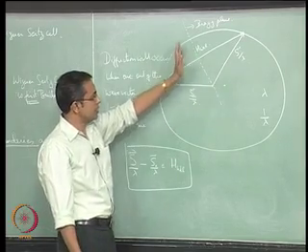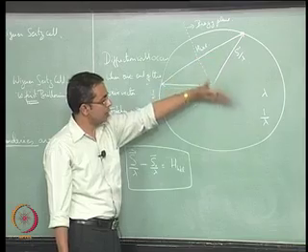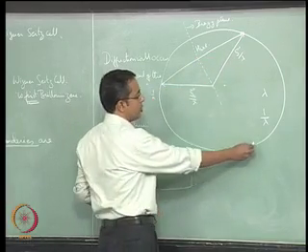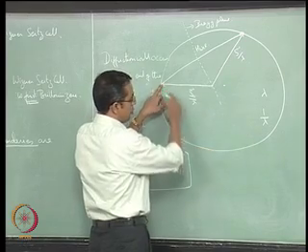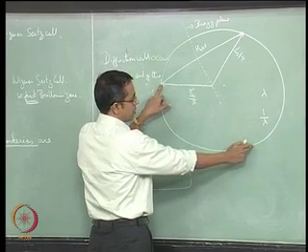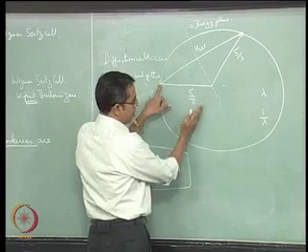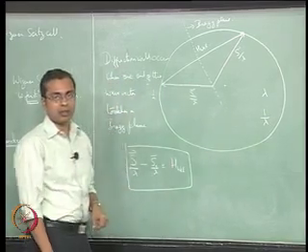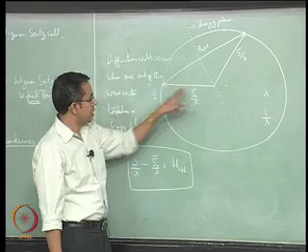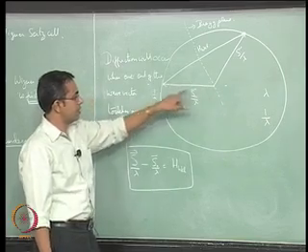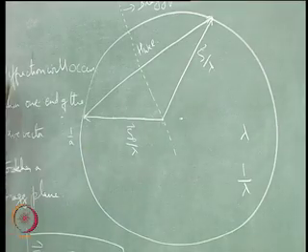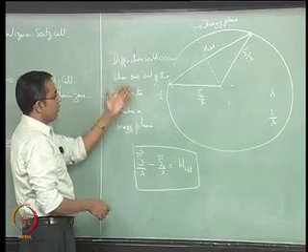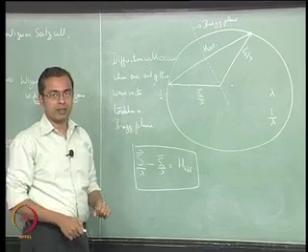No matter which lattice point you take, where this is getting satisfied, if you draw the line joining the origin to that lattice point, that is a valid HKL, you draw the perpendicular bisector, it will go through that point. So one end of this wave vector will always touch that Bragg plane. Therefore whenever diffraction occurs, one end of the wave vector will touch a Bragg plane.